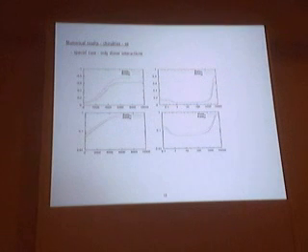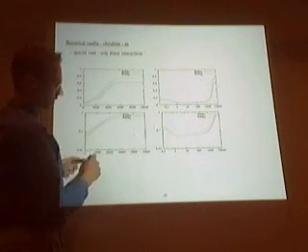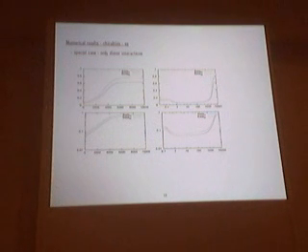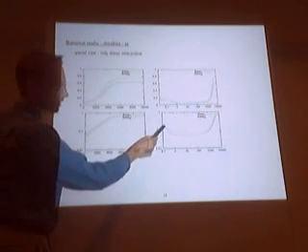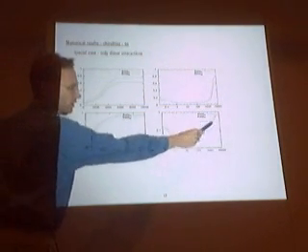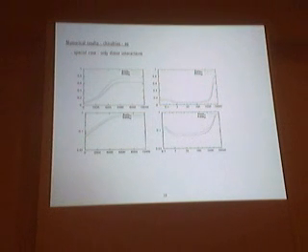So this is only dimer interactions. This doesn't have any monomers in it anymore, and we get very similar results to what we had before. That's the symmetry breaking one. We still get exponential growth of the E. We get this slight, quite interesting effect where we put in a slight initial perturbation in order to see symmetry breaking, and even though we put in a slight perturbation, it decays almost down to nothing and then grows again a lot later on.